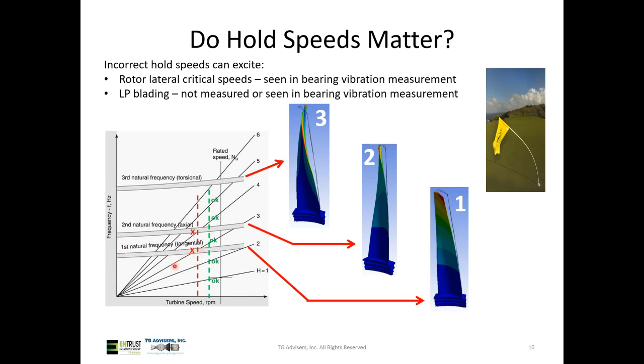So the challenge here is that you don't have any instrumentation on your unit that would tell you if you have blade vibration. You do have measurements at the bearings, but those are looking at rotor vibration. They're not looking at blade vibration. So you could be holding at a bad speed and causing damage to your blades, but not knowing it. So the best way to protect against this is just to adhere to the hold speeds that are in your instruction manual. And if you were to get a retrofit LP rotor, making sure that you get updates to those hold speeds as needed.